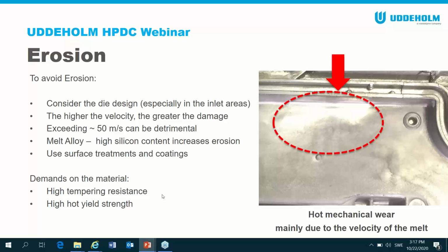If we now go on to erosion, what you can see here is a picture of a cast part. This is the left-hand gate entry on a heat sink part. And you can see here there's washout erosion there just where the gate is. Now this is a Dievar tool. It has very, very good life. Actually, as you can see it now, this is 250,000 shots. But before, when it was just Dievar, it did 150,000. When it was H13, it would have done something like 80,000 shots. So the company first went to Dievar and then went to Dievar with coating. And we'll go through the process now.